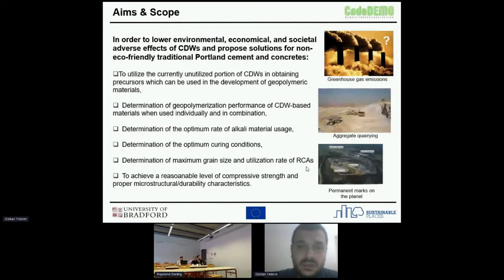And to use these materials in geopolymeric binders, which are free of ordinary Portland cement, you need alkaline activators such as sodium hydroxide and sodium silicate or calcium hydroxide. So another question is to determine what will be the optimum rate of alkali material usage. Another issue is how you're going to cure these materials, because as in normal concrete, you need to cure your material, but this is a bit different in the case of geopolymeric materials.